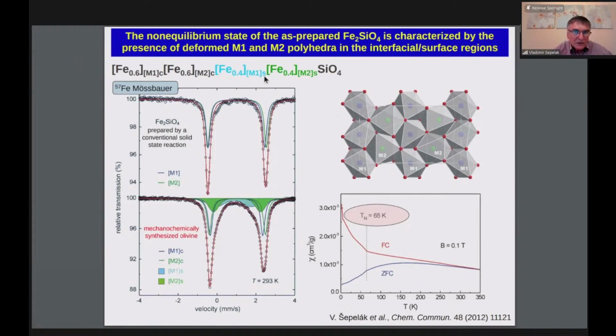And you see that about 40% of ferrous ions in the material is in the interfacial surface layers of mechanosynthesized nanoparticles. And if we measure Néel temperature or susceptibility, depending on the temperature, we can see that the Néel temperature of mechanosynthesized material is 65 Kelvin. It's the same as for bulk material, but we see now a very broad distribution of this Néel temperature. It's not so evident a peak like in the case of bulk material.